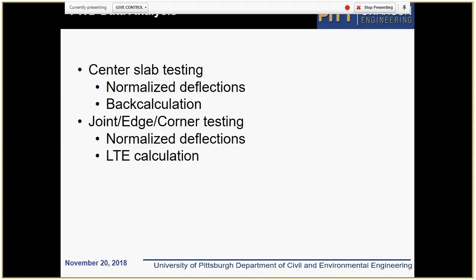We also looked at the deflection data, and those results are actually quite interesting. Looks like I'm running out of time, so I will show only a few results. Basically, what we've done, we did a simple analysis of normalized deflections, and later we performed the calculation using two techniques, and we found that those results were quite strange. First of all, the variability was higher than we expected, and the second is the calculated values were higher than we would expect for a pavement of this thickness at this age. We're still trying to explain these results, and we're checking our calculations.